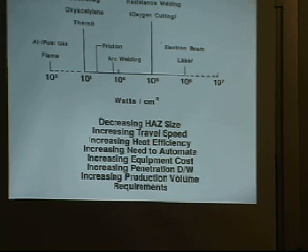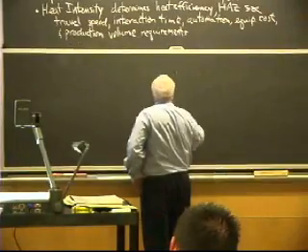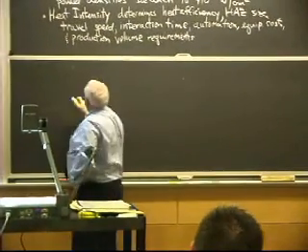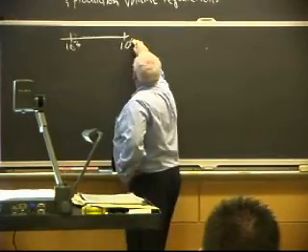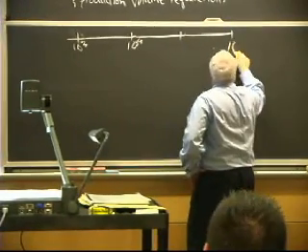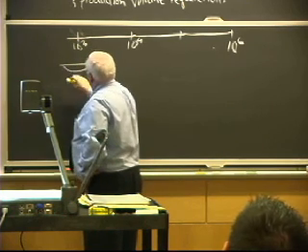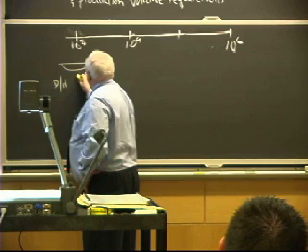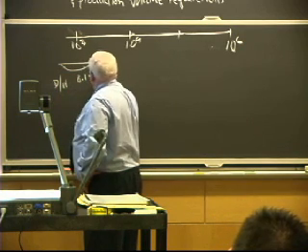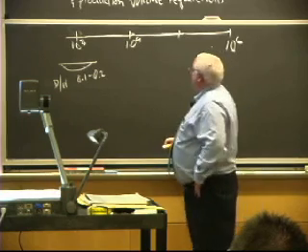What we didn't talk about was the depth to width ratio of the weld pool. It turns out that if I'm over here at 10 to the third, I will have a weld pool, if I did an oxyacetylene weld, that might have a depth to width ratio, that's what we usually talk about, of 0.1 to 0.2, or 5 or 10 to 1 width to depth.